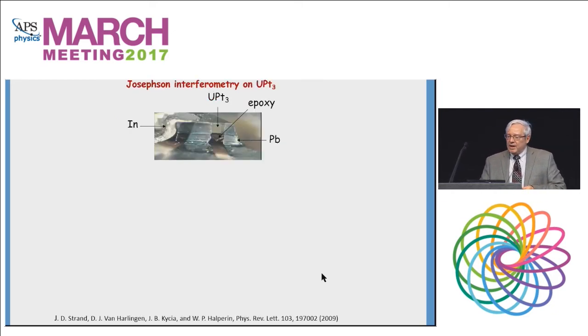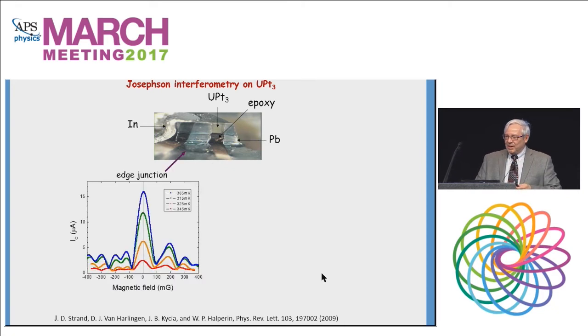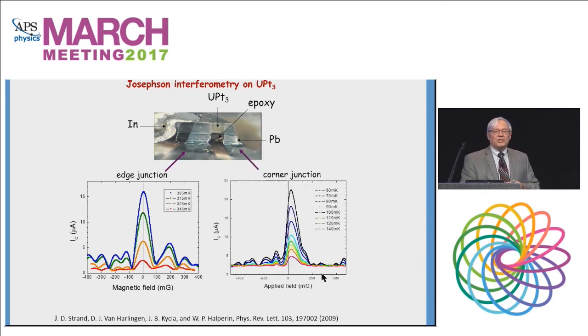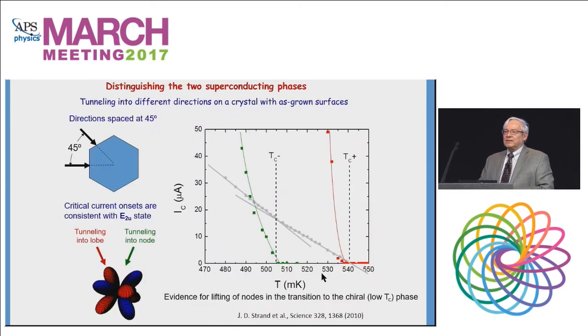So here are experiments on UPt3 using beautiful single crystals from our chairman, Bill Halperin, and done by a student of mine, Joel Strand. In edge junctions, here's a junction on the edge, a junction on the corner. The edge junctions show Fraunhofer-like patterns. The corner junctions show a definite polarity asymmetry, which is indicative of a complex order parameter. And we were able to actually do experiments directly to see the node lifting and see that this material actually has two distinct superconducting order parameters, one of the few materials still known to exhibit that phenomenon. You can see here the turning on of the critical current if we look into the lobe, and the lower critical current if we look into the node of the superconductor.